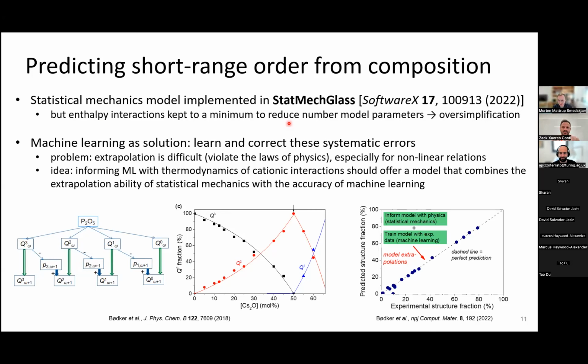So I'm wondering how you tackle uncertainty in your modeling, given that, of course, your data is empirical, and as we know, even with the way you collect data, there are going to be errors there as well. Yeah, so the whole curation of the data is really a big thing. For example, these compositions that, as I said, are typically used as input, many times will be nominal. People have not even measured the composition, so that gives a huge error. In some cases, they will be measured.